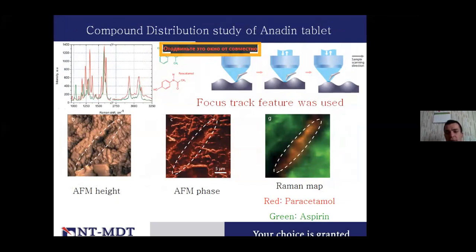And here is example of some application to measure the tablet, which contain of the two components. One is a paracetamol and another is aspirin. So when you measure the topography, AFM height and AFM phase shift, you can see almost nothing on the image, and you cannot understand which components corresponds to which area. But when you measure the Raman shift, then you can see clearly which area corresponds to which material, because you have a database of all the material and Raman peak shift, and you can understand, okay, well, this area in the center corresponds to paracetamol. The other green is the aspirin.